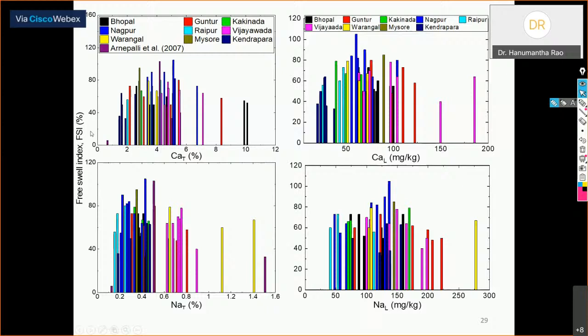There is a total amount of calcium that exists in that soil, and from that soil a certain amount of calcium can leach out. We do not know whether the total form is the realistic parameter or the leachability is the realistic parameter. Therefore, we tried to correlate both the total form and the leachable form of calcium with the free swell index, and we have seen a beautiful relationship. You can see in almost all cases, with calcium or with sodium, there is an increase of free swell index with increase in the calcium or the sodium content.